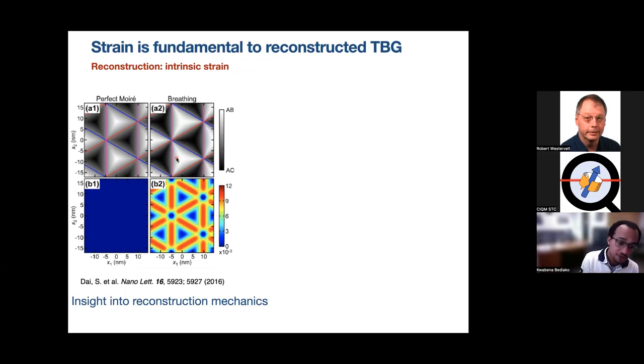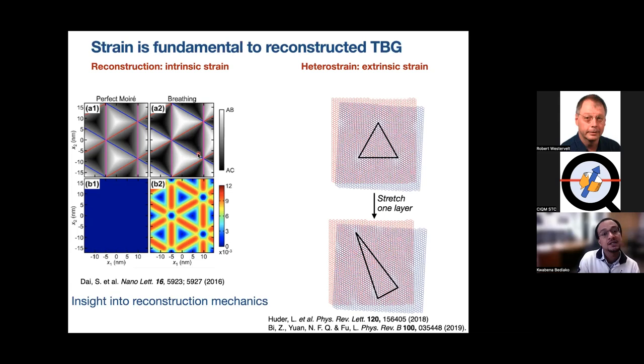relaxation, or atomic reconstruction as it's called, is an intrinsic material property of these twisted structures. And so we have to understand this process, and because these relaxations are predicted to introduce intralayer strain that builds up as a direct consequence of the relaxation, we wanted to measure strain as a conduit to quantitatively understanding the relaxation process and measuring it. There's another type of strain which is extrinsic. This is one example. This is uniaxial heterostrain, and this is just a form of strain that arises where one layer is stretched relative to the other, and so that deforms their moiré superlattice and breaks its symmetry.